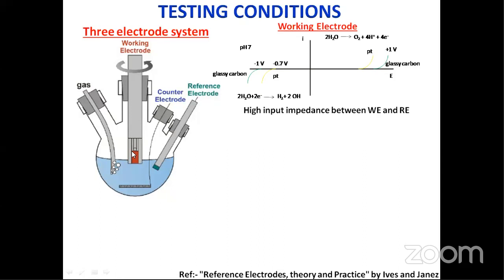If you have carbon active electrode material, you cannot directly use that bulk material as a working electrode. You have to process it and fix it on a current collector. So the selection of the current collector is also very, very important. Say for example, if you have an active metal oxide coated on platinum, the hydrogen evolution occurs at minus 0.7 volt, and of course the oxygen evolution also occurs much faster than on a carbon based substrate. So the selection of current collector is very, very important.